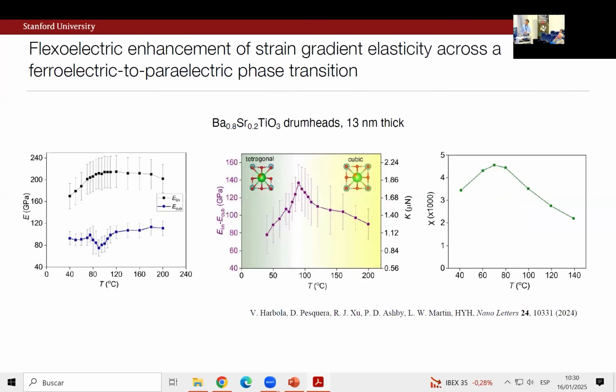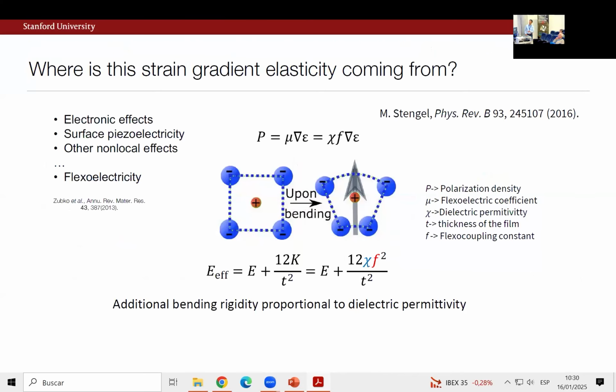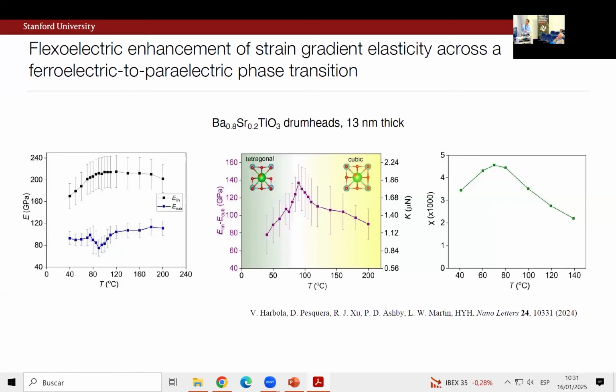So more recently, and actually I guess with local help now, from Berkeley days, but in any case, if you believe that indeed this could be of dominant flexoelectric origin, how would you go after that? Well, one thing you could do is to go across the paraelectric to ferroelectric transition, right? That's where the dielectric response of the lattice maximizes. And indeed, in this lovely system that we got to play with, this has been compositionally tuned for an ordering temperature a little bit above room temperature. And again, if you take this kind of difference between linear and cubic response, you have a nice peak associated with that